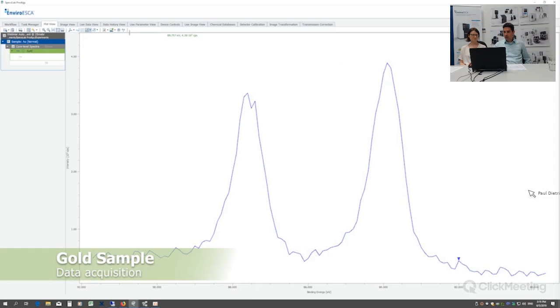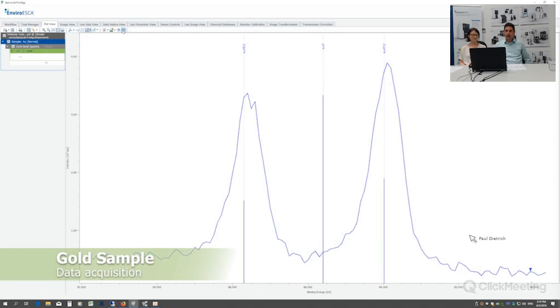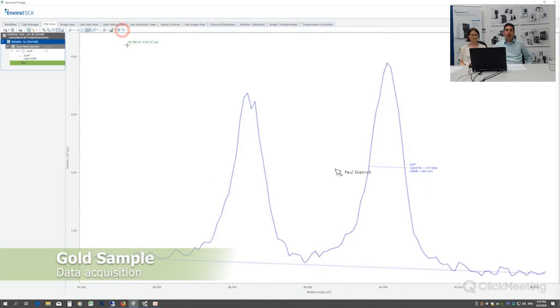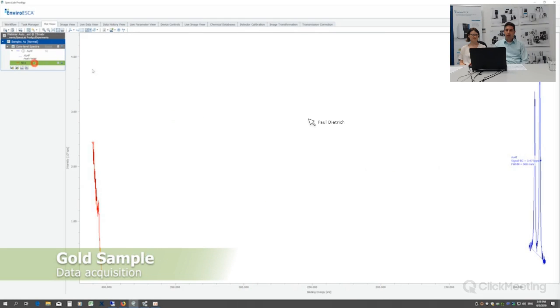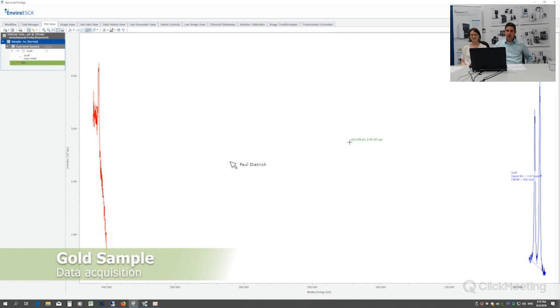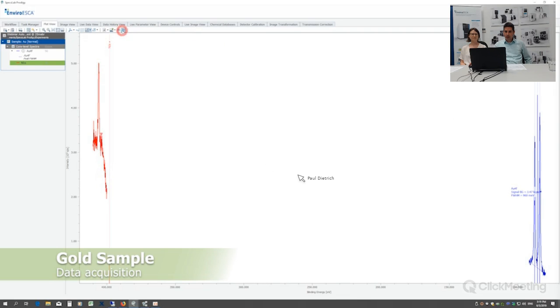Additionally, there's also a nitrogen spectrum taken to have the gas line, as Andreas said. You can at the same time check if the gas is still present in your analysis section. If you do it under different environments, then you can check if the gases are present or if something is wrong with the conditions you want to treat your sample with. In this case, it's the nitrogen spectra, and for the gas peak, it's a little bit higher than the literature value of 400 eV. It's around 406 eV binding energy because it's the signal of the molecular nitrogen.